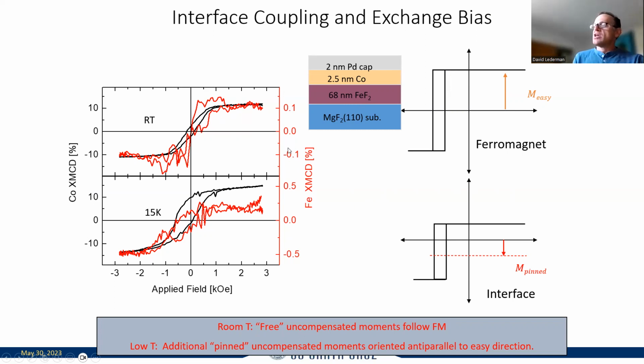Now, the other thing you have to know about this technique is that it's extremely surface sensitive, because you come in with X-rays and you detect electrons. The escape depth of the electrons is just a few nanometers. So we're only probing down to probably just this interface, not much more than that. So this is all coming basically from the interface for the iron signal.